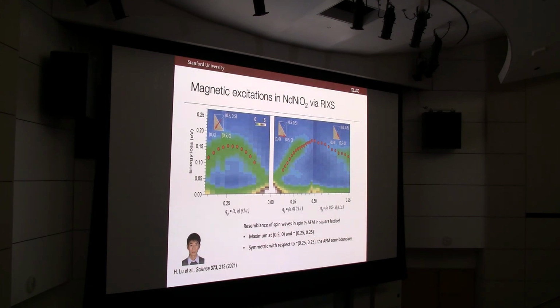So this is what we found. This is the parent neodymium nickel O2, and you can see the intensity distribution in high symmetry directions of what looks basically like what you would expect for spin waves in an antiferromagnetic square lattice. So this is quite interesting and in some sense surprising. It's quite a large energy scale, going up to about 200 meV.